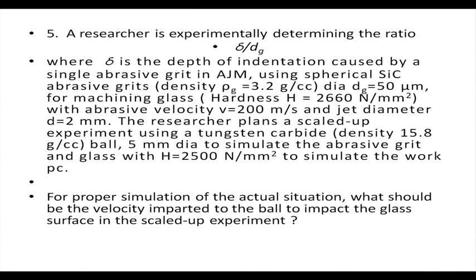Okay, that is good. So, what he has done is, he is selecting the case of abrasive silicon carbide grits with density 3.2 grams per cc, diameter 50 microns, and the material to be glass with hardness of 2660 newtons per millimeter square, with abrasive velocity equal to 200 meters per second and jet diameter d equal to 2 millimeters.